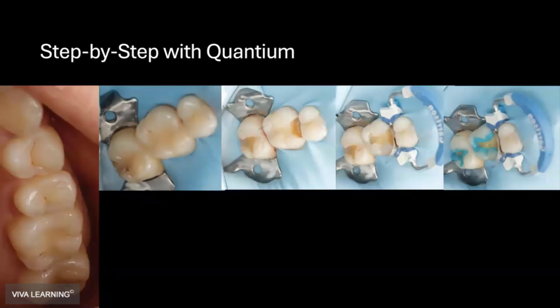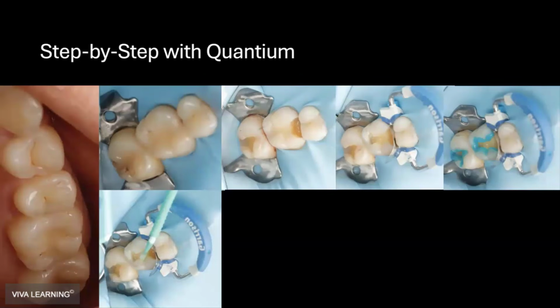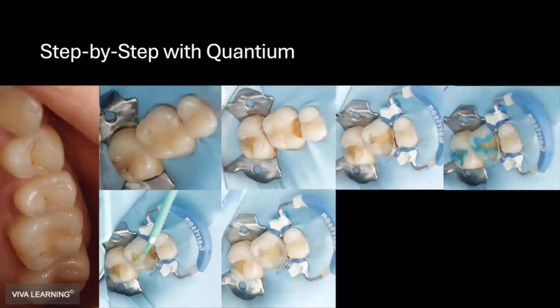Selective etch. I always do selective etch. Scrub the bonding in for 10 to 15 seconds. So make sure if you're doing selective etch, you must scrub that bonding into the cavity walls and the floor and the dentin for 10 to 15 seconds, because if not, it doesn't work. And you're supposed to apply at least 2 coats of adhesive if you're using All-Bond Universal.